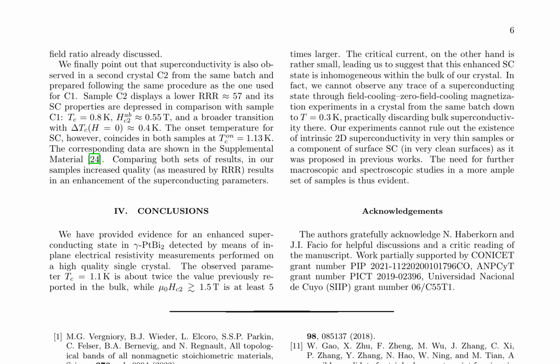Trigonal PtBi2, a topological material candidate, exhibits enhanced superconducting properties in high-quality single crystals synthesized with a residual resistivity ratio of 130, significantly higher than previously reported values. This improved crystal quality leads to a higher superconducting transition temperature of 1.1 K and a critical field at least 5 times larger than previously observed. Notably, the study reveals a small critical current, suggesting an inhomogeneous superconducting state within the bulk of the crystal.